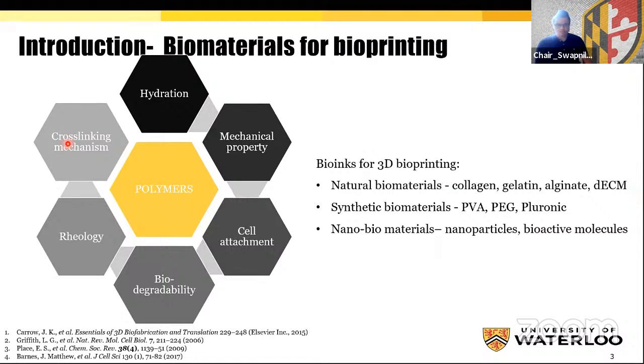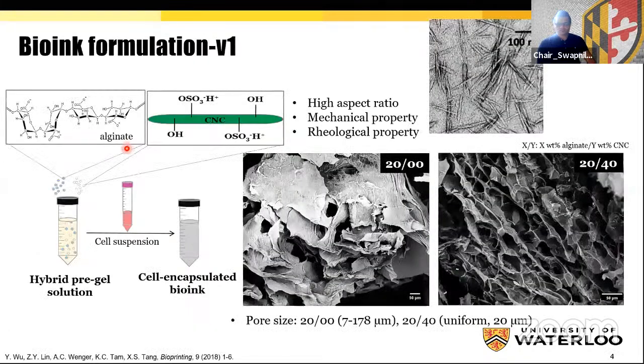Therefore, suitable bioinks can be natural biomaterials, synthetic biopolymers, or nanobiomaterials. In our group, we first selected alginate and cellulose nanocrystal as the bioink formulation. The dimensions of the high aspect ratio CNC from the TEM image are 200 to 400 nanometers in length and 10 to 20 nanometers in diameter. It's a very promising nanomaterial in bioprinting due to its optimal mechanical and rheological properties.